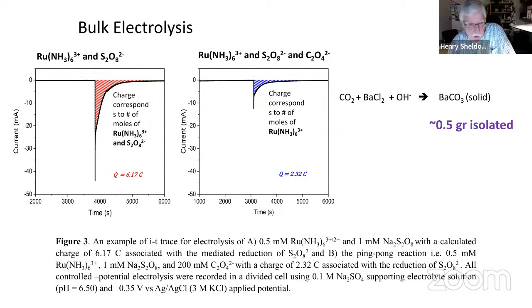This is a really simple experiment. And then you take the same solution and you add oxalate. And what happens is you measure a charge, but it only corresponds to the number of moles of ruthenium in the solution. You're no longer getting charge resulting from persulfate reduction at the electrode. It's all happening homogeneously in the solution.